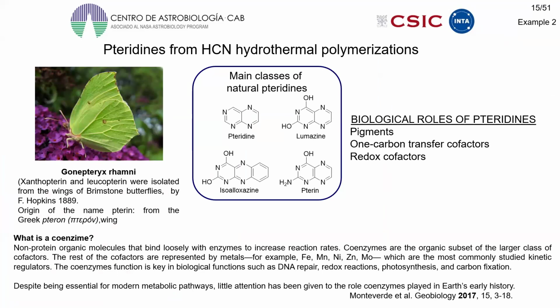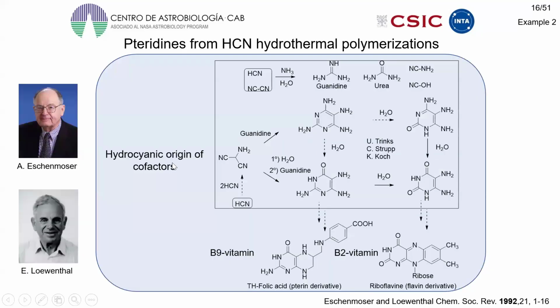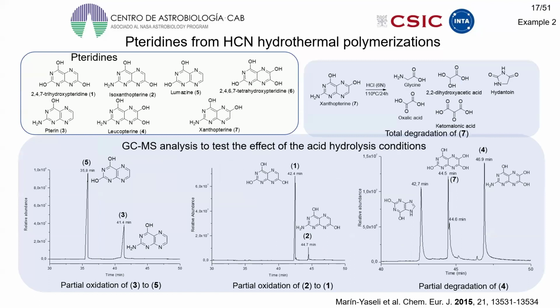Our next example is the identification of pterins in hydrogen cyanide polymers. These compounds are interesting because they have a variety of important biological roles, such as one-carbon transfer cofactors and redox cofactors. Eschenmoser and Loewenthal were the first authors to propose a hydrogen cyanide origin of some cofactors. Thus, some years later, we developed an analytical method to identify pterins by GC-MS. And again, the hydrolysis conditions have a significant effect on the identification of those molecular targets. We observed partial oxidation or total degradation of the pterins after hydrolysis.